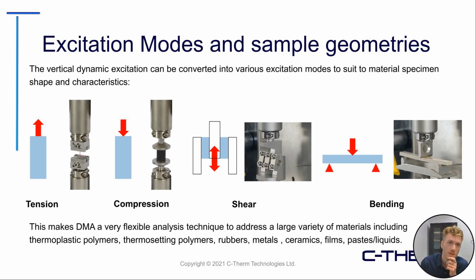So when we have a vertical dynamic excitation, we can convert this into different excitation modes through the sample geometry itself. So we can do this through tension, a uniaxial tension experiment, compression through compressive forces on a material, shear, which is one of the more used for tire applications because you get 100% transformation of the shearing force into the material itself, or bending, which is more apt to fatigue type testing. So because we have all of these different types of sample geometries, different excitation modes, different frequencies, temperatures, this makes DMA very applicable to a large range of materials for testing thermoplastics, rubbers, metals, ceramics, films, paste, and other liquids as well.